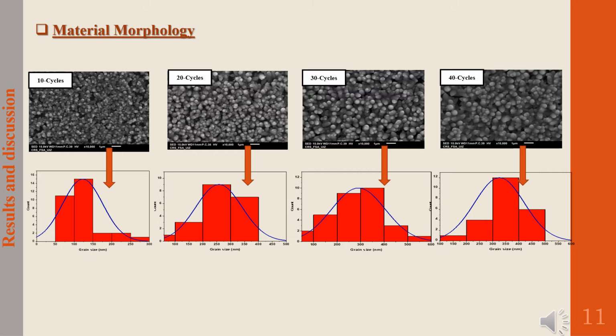Now we discuss the results part. From the scanning electron microscopy analysis, we noticed that the films are made of nano-sized grains homogeneously distributed on the substrate surface. The images were subsequently processed by image software to determine grain size distribution. The average grain size measured from scanning electron microscopy images increases with the number of growing cycles.